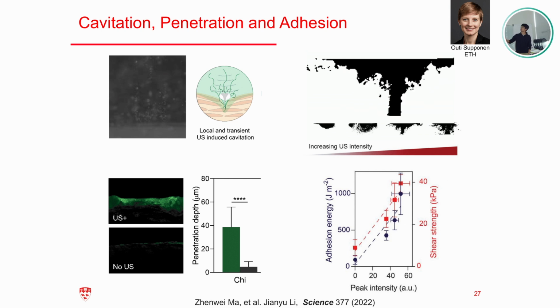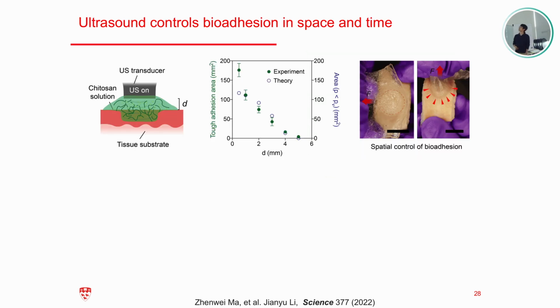As you can see here, without ultrasound, it doesn't get into the skin, but with ultrasound, you get a much deeper penetration. Further, we also checked the correlation with ultrasound intensity. So here is a microbubble cloud under the ultrasonic probe, and we can play with the intensity and further measure the adhesion performance. As you can see from these plots, both the adhesion energy and the strength are proportional to the cloud intensity, or the ultrasound intensity you apply. So this further supports the correlation between the cavitation and the adhesion.